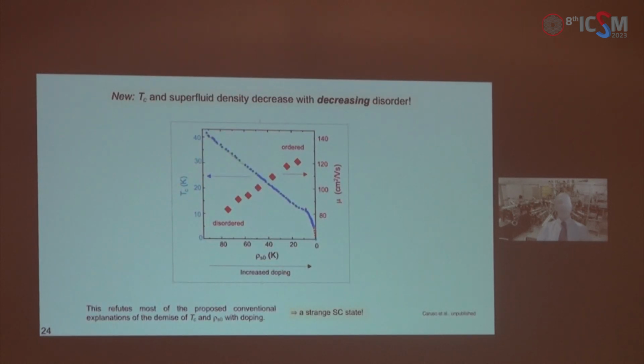Now, in the last few months, we have done a new experiment that's not yet published. Here, we're looking at one and the same strontium cuprate film, but we tune the mobile carrier density by ionic liquid gating. We were able to tune Tc by more than a factor of 2. We measure the temperature dependence of resistivity and the penetration depth operando, which means as we are gating the sample, and we can change the gating and the doping level of Tc in fine increments.